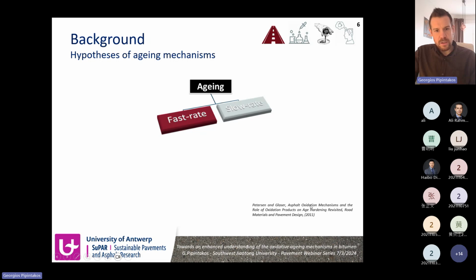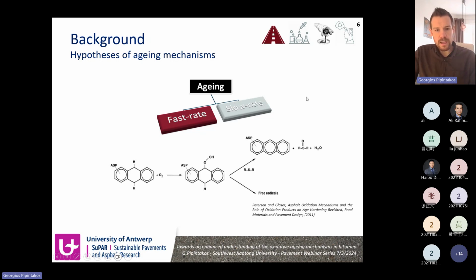Petersen, as you can see also in the reference, also assumed that if we take a representative molecule of bitumen, for example, a dihydroanthracene, and this is later oxidized from the oxygen that exists in the atmosphere, then after an intermediate hydroperoxide, we can have two possible chemical routes for the fast rate phase. Either this hydroperoxide is aromatized, and this is accompanied by the formation of sulfoxides, or if this hydroperoxide is thermally unstable, free radicals will be formed. And these free radicals, he also claimed, can play an important role for the continuation of the slow rate phase, which in reality is the long-term aging that affects our roads for years.